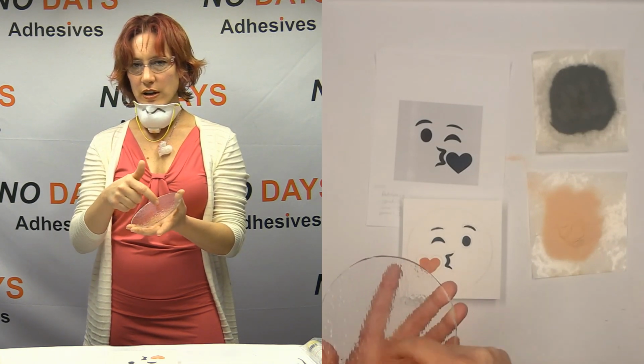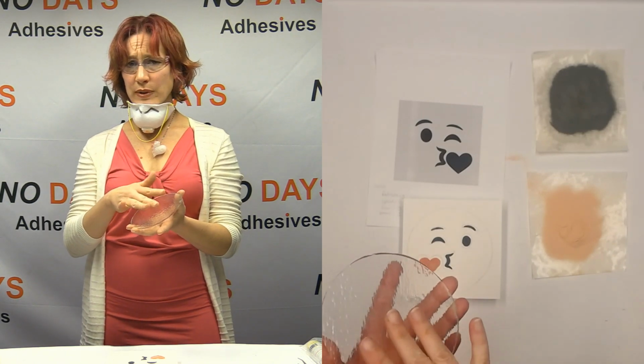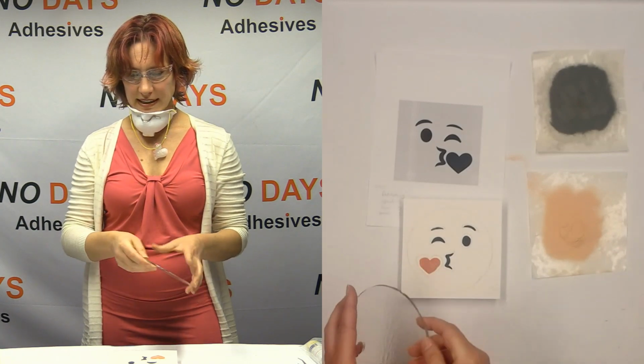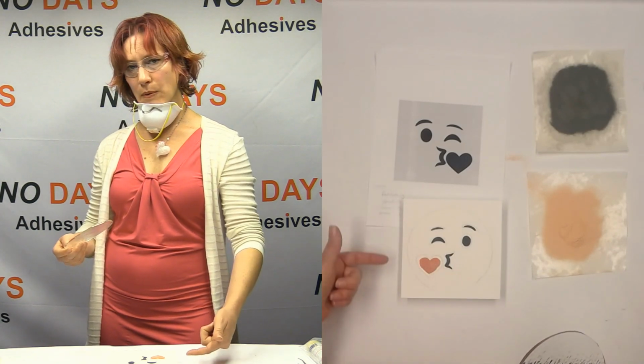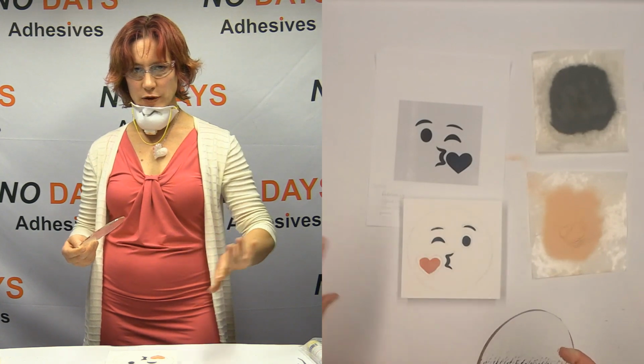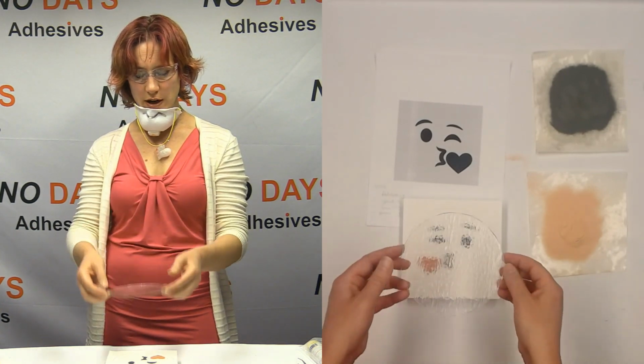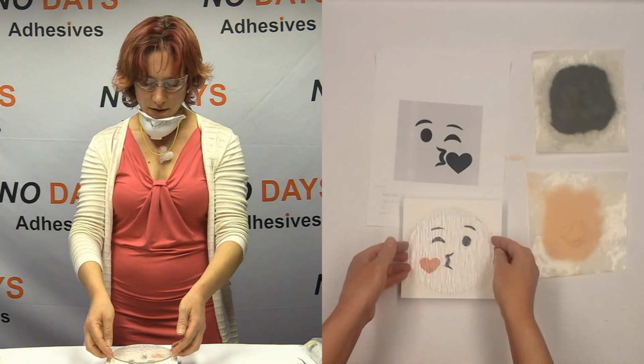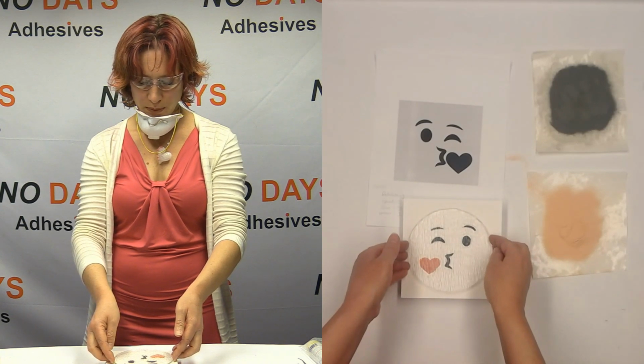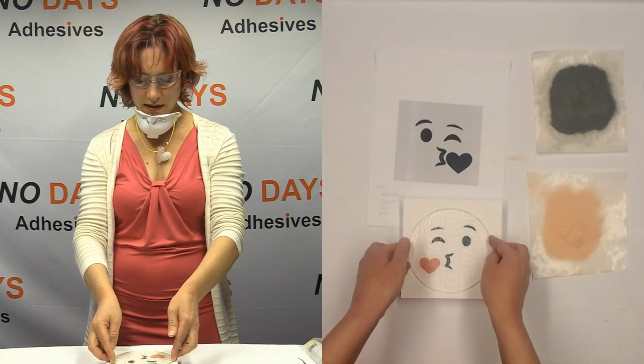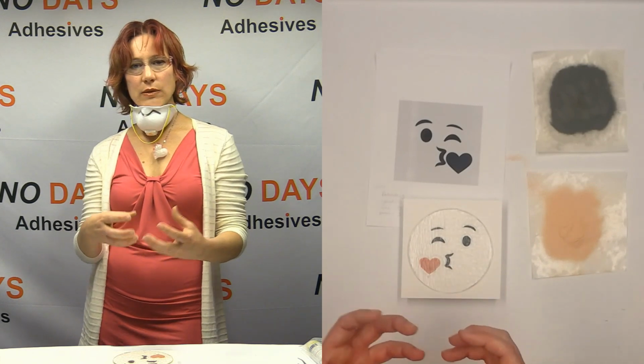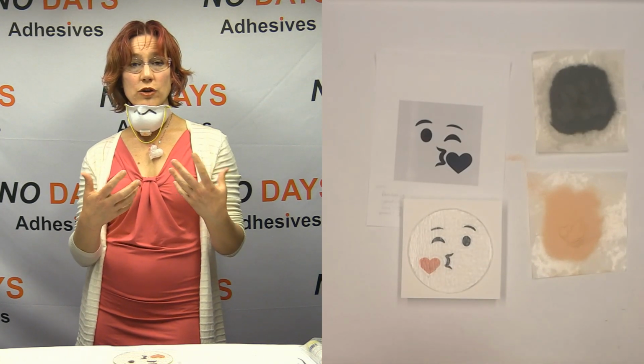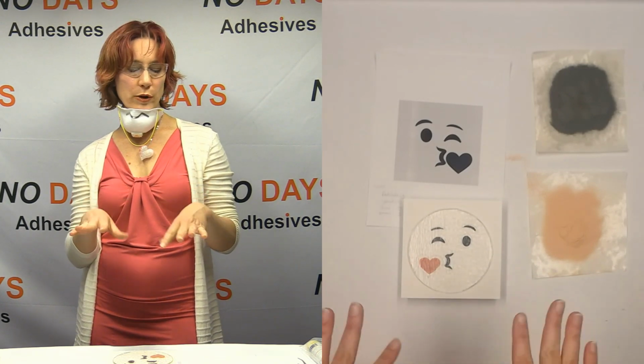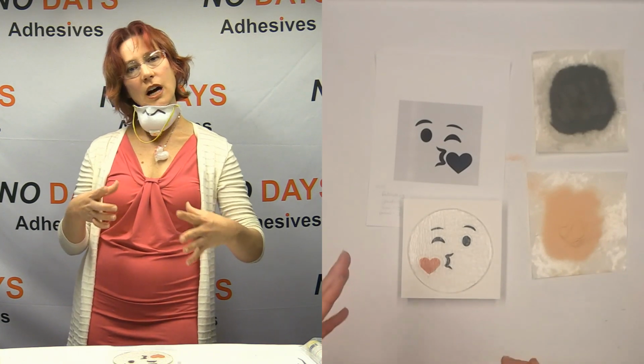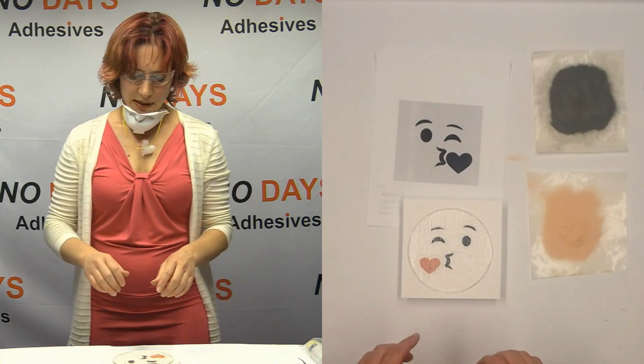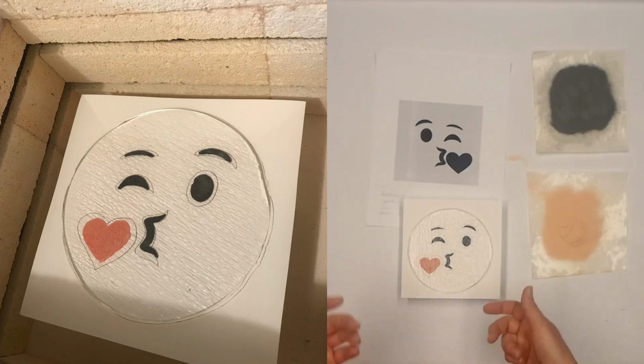The side with the texture on the glass, if there is a side with texture, I'll put that down, because one, I've got the fiber that's helping me to let any extra air escape, but now I've also got the texture. It's creating channels for me, and that's going to help any extra binders burn off as well. So if any of the binders get caught underneath the glass while they're burning off, they can end up turning to charcoal and they'll be brown, or your powder won't quite be the nice vivid color that it's supposed to be. So this guy is ready to fire, so I'm going to go ahead and put this in the kiln.